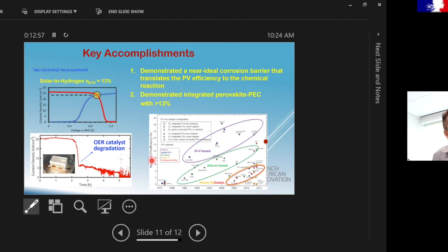Finally, if you look at the reported STH, this refers to the solar-to-hydrogen conversion efficiency. This is kind of where we are, right? And of course, this is in 2021 right now. So this red dot corresponds to that, and that's where we are. We are not very far away from some of the record values, which are 16, 17% for solar to hydrogen, as far as I'm aware. But we are doing this with perovskite solar cells, whereas this record exists with III-V semiconductors. The cost of III-V semiconductors is about $30,000 per square meter, as opposed to perovskites, which is about $20 per square meter. So we are very excited about this, and I feel like this is going to be a very nice, important direction going forward.